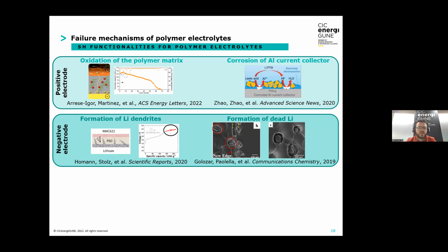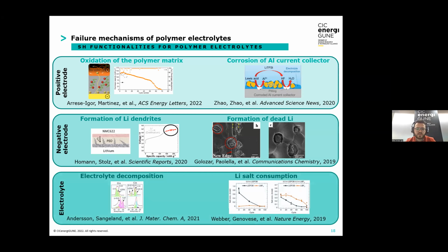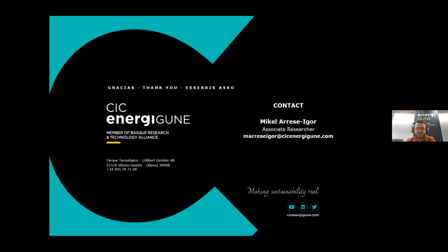And in terms of the bulk electrolyte, the electrolyte decomposition and the lithium salt consumption, which is generally related with the electrodes, but it's a problem of the final bulk conductivity of the electrolyte. So all these fields are places where self-healing would have a bit of research to be done, and where it can, in my opinion, improve the problems for solid-state batteries comprising polymer electrolytes. So this is my last slide.